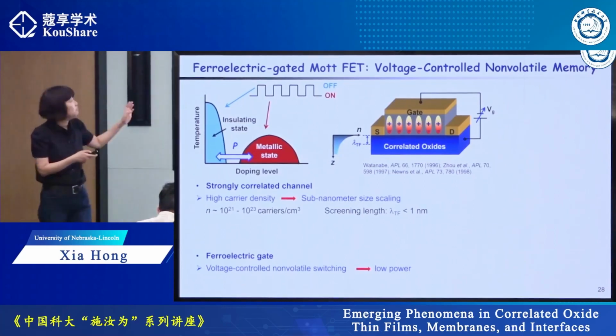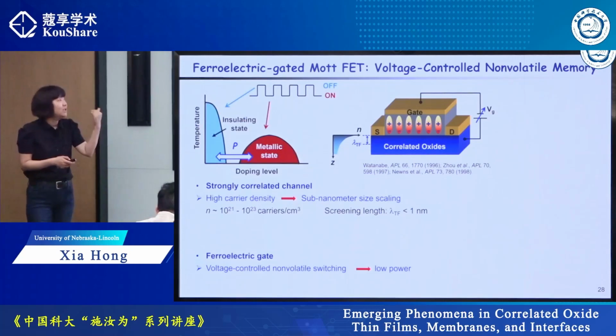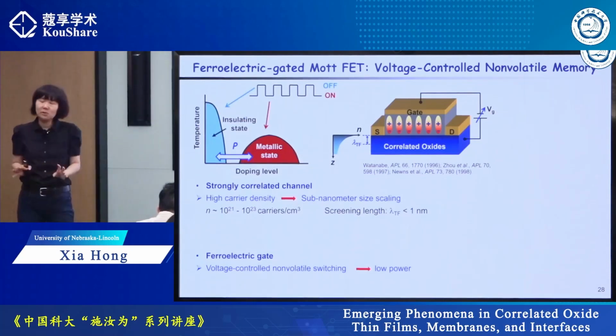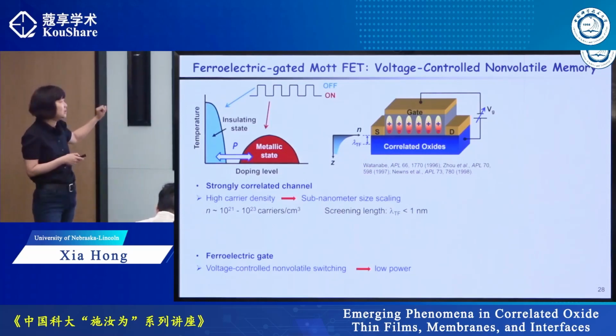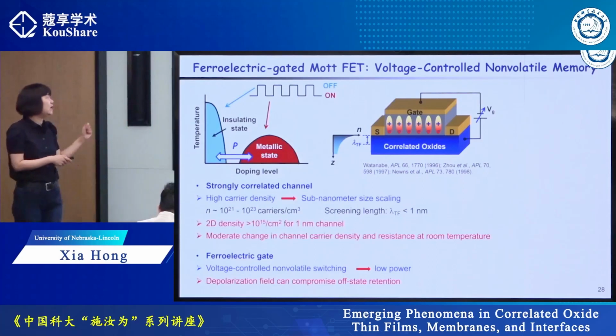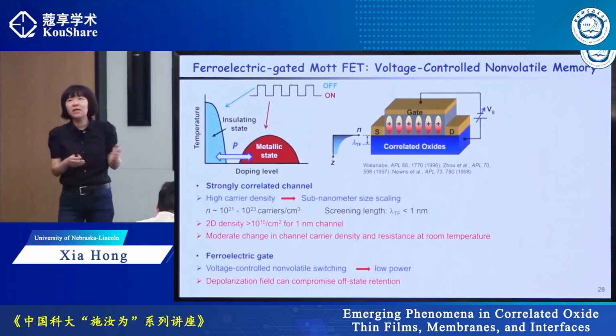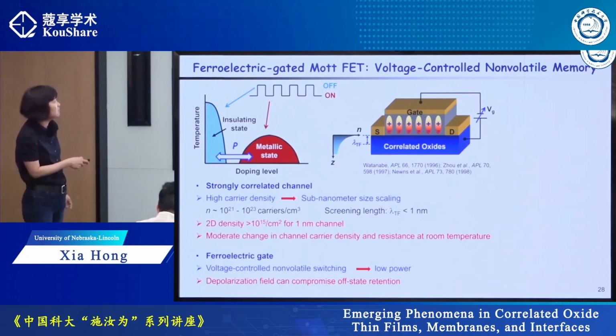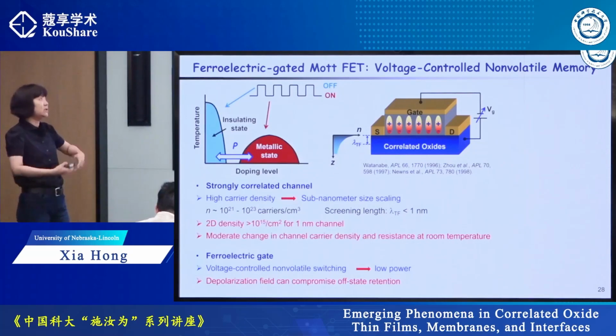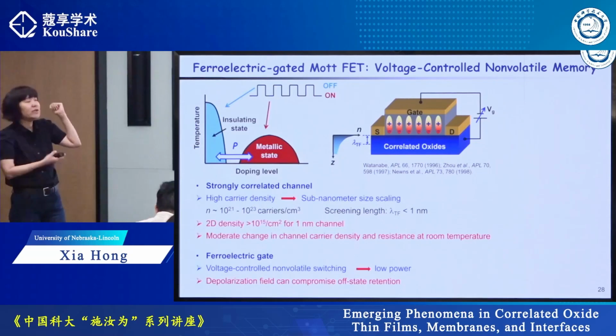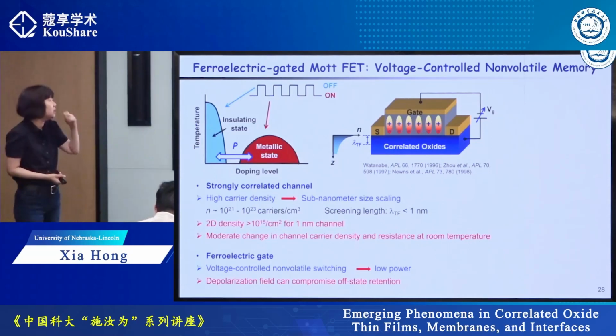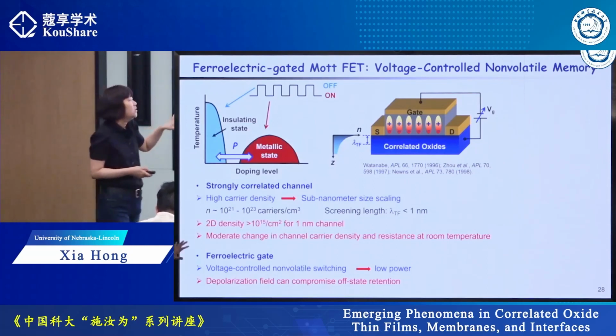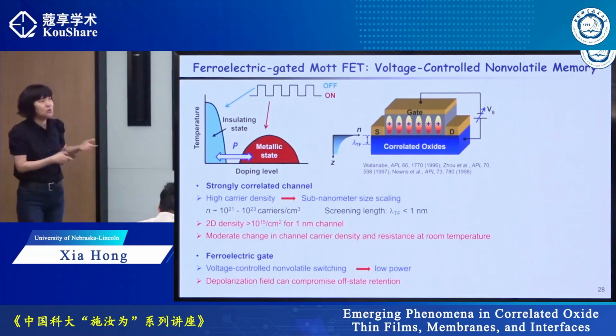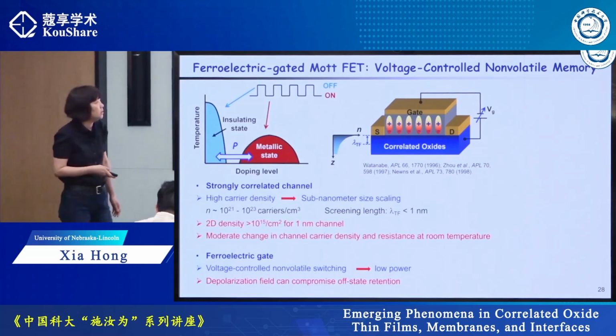It was proposed almost three decades ago with not much success, because the key advantage is also the key curse. If you have very high carrier density, that means I do not have a solid state gate that produces enough displacement field to tune the carrier density. That means the on-off ratio will be very small. And in the insulating state, ferroelectrics are known to have a depolarization effect. If you do not have enough switching charge, you get spontaneous switch back, so the sample is not stable. So basically, what we want to do is address these two challenges to realize the full potential of Mott transistors.